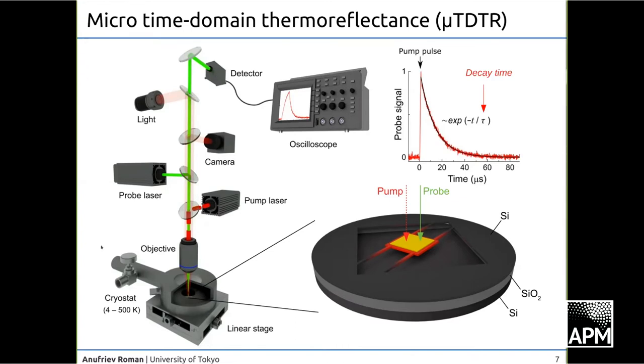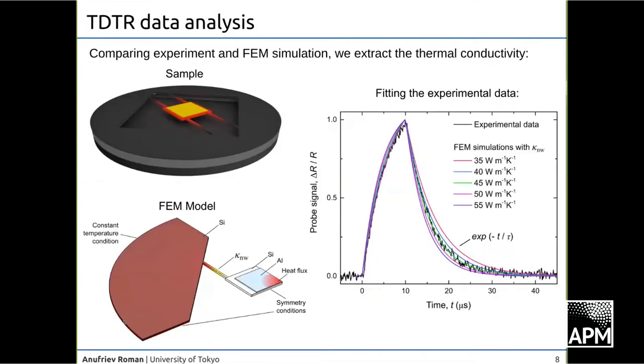Yes, and we have a cryostat, by the way. The cryostat will allow us to measure heat conduction in a wide temperature range from 4K to more like room temperature in this setup. And then from this measurement, we can extract thermal conductivity by using finite element method simulations. We basically simulate exactly the same experiment, and then we fit our curve with different parameters of thermal conductivity. We can see that only one of them actually fits the experiment. It's the one of 45 watt per meter K here. So we say, okay, then the thermal conductivity of the structure must be 45 watt per meter K.